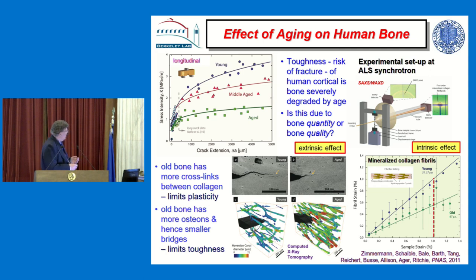What's the intrinsic mechanism? Well, we use a technique called small angle X-ray scattering. We put a little piece of bone in a testing machine in the X-ray synchrotron, and we use wide angle X-ray scattering, which focuses on the mineral. The mineral is crystallographic, so we can see the strain. That's not so important here, but we can also use small angle X-ray scattering to look at the collagen. Now, the collagen has mineral on it, and it has a very unique spacing of about 65 nanometers. So that looks like a crystallographic material in terms of scattering, and we can measure the strain in the collagen.